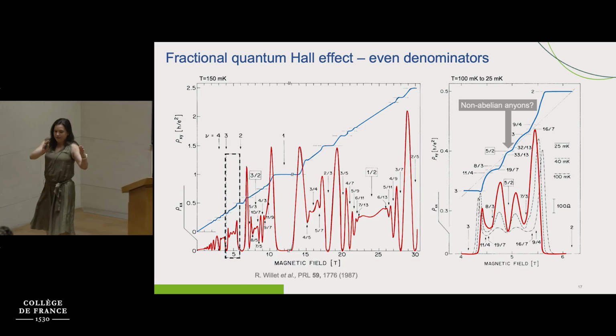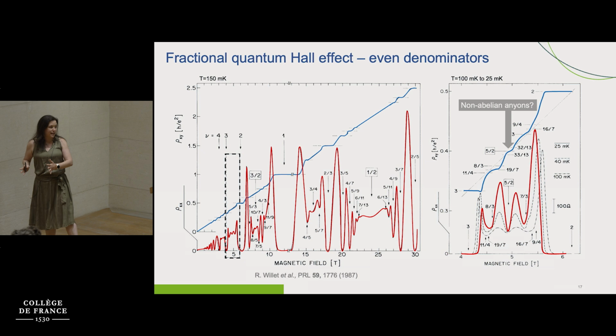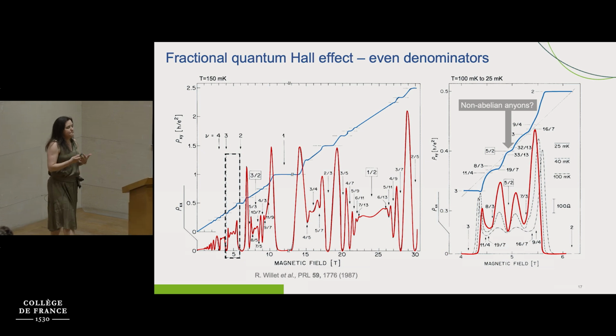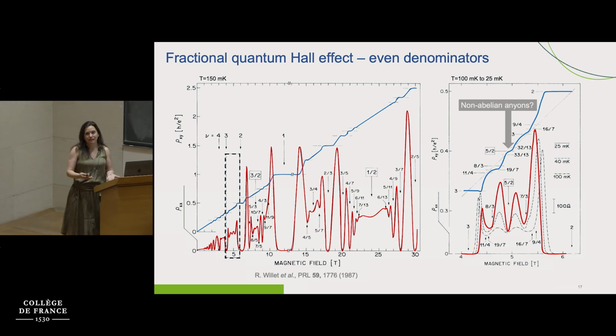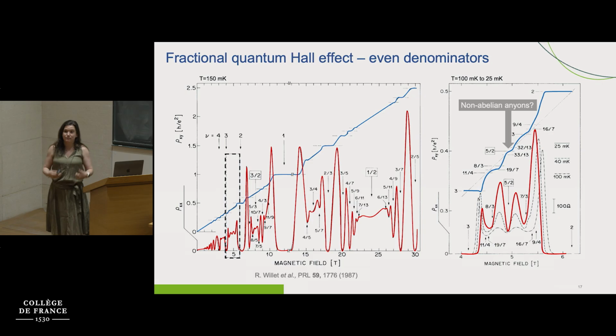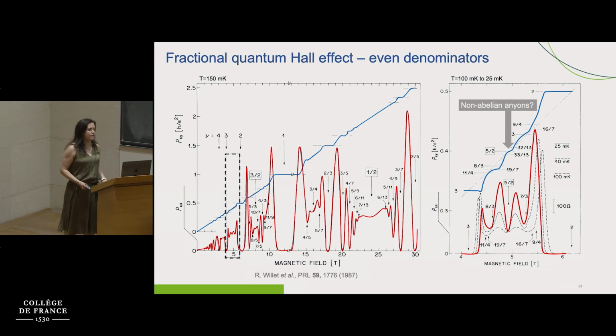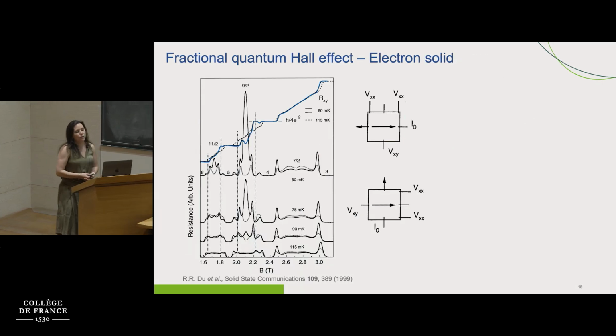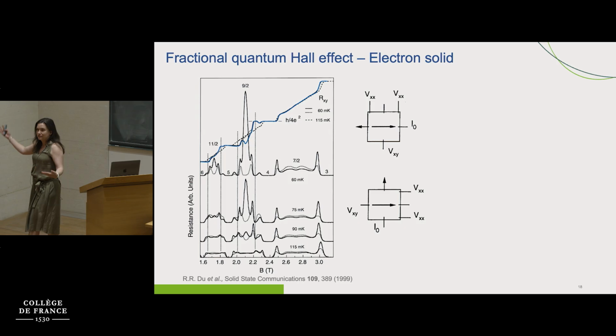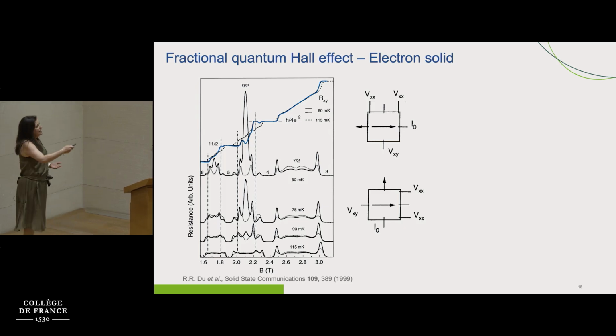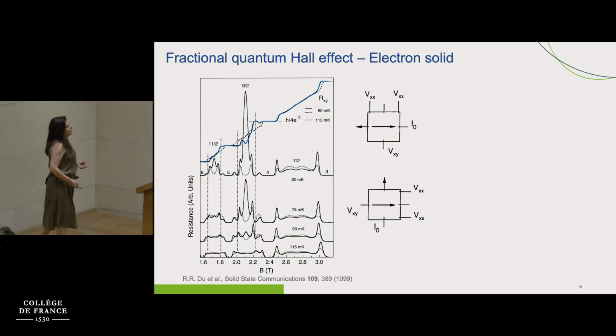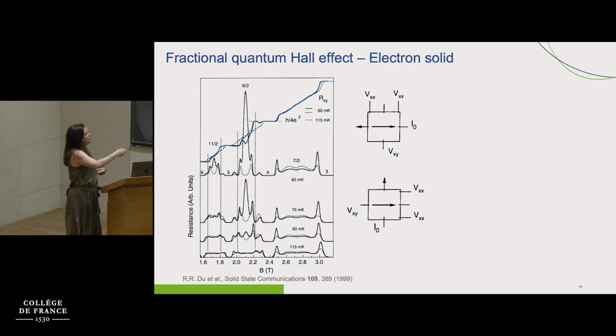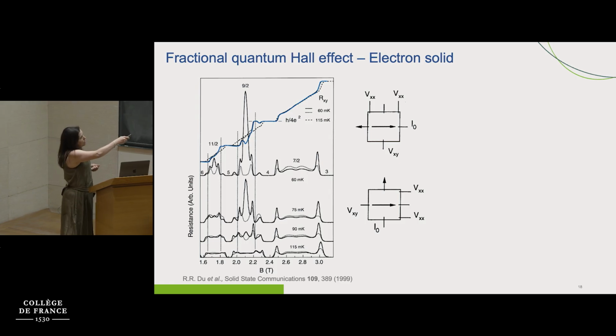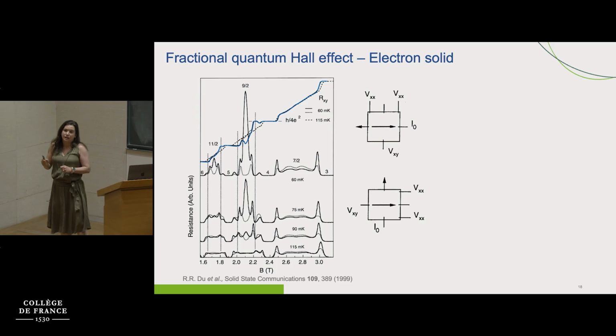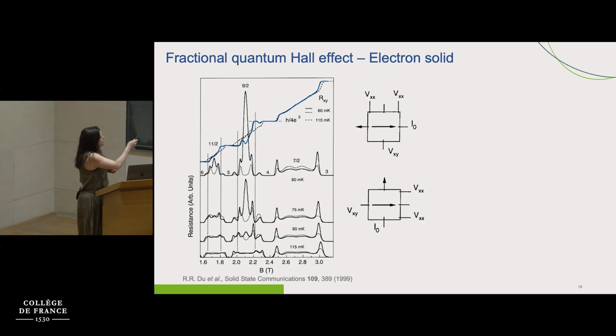So we have integer quantum Hall effect, fractional quantum Hall effect, but if we keep cleaning our sample, if our sample starts to become even better than before, we're going to have something that is called an electron solid. Okay? This electron solid was first observed at the end of the 90s, by the presence of a strong anisotropy in the measurements of the longitudinal resistance and the Hall resistance as well.